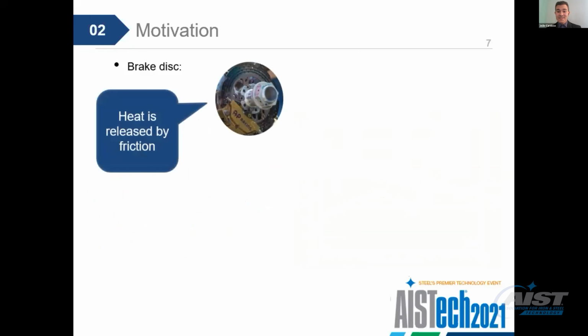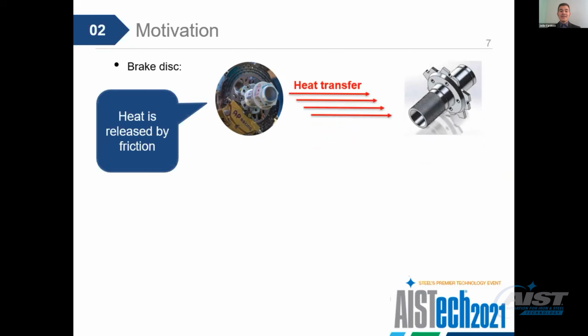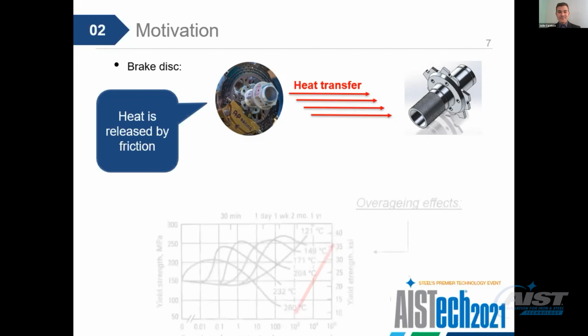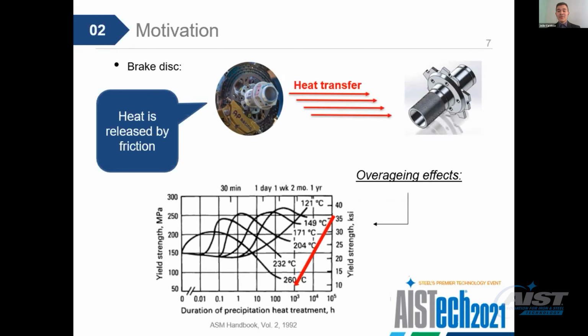So getting back to the problem, a hypothesis to explain what the possible cause was the thermal influence caused by the brake discs. I will explain. The brake discs are the components that use the friction in order to stop the car's movement. And this friction releases a lot of heat right next to the wheel hub. And with conduction, convection, and radiation, the heat is transferred to the wheel hub, affecting the heat treatment and causing a phenomenon called overaging. This phenomenon causes a decrease in strength because of the coalescence of the fine precipitates.